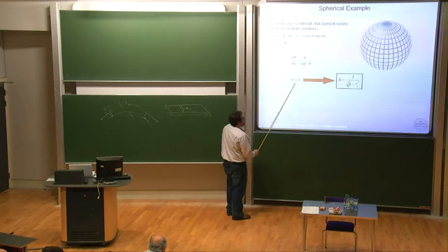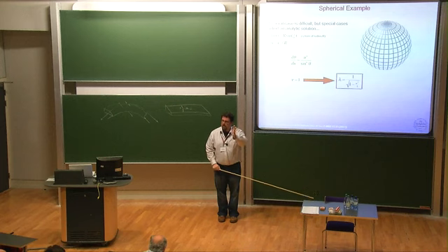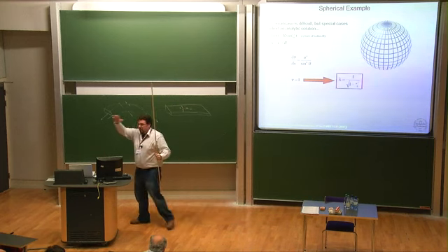But anyway, if it is 1, then there's nothing to this. You just directly integrate it and solve for lambda, and you get this simple form. So if you wanted to have a nice smooth sphere pop out of the plane upon illumination, you would arrange the intensity of your light beam to vary with the rescaled distance in this simple way, and you would shine it on a thin radial texture of nematic glass. And it would make this little spherical cap for you.